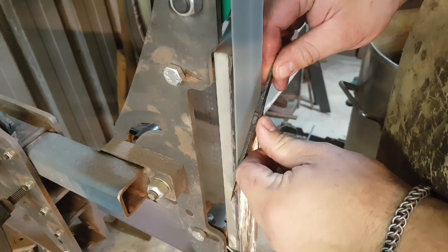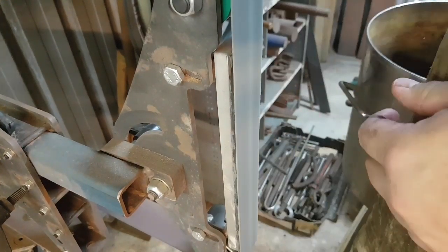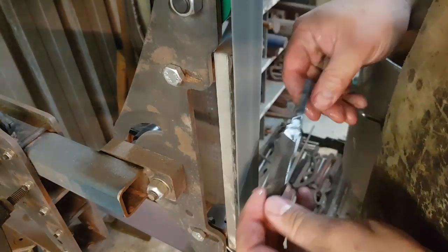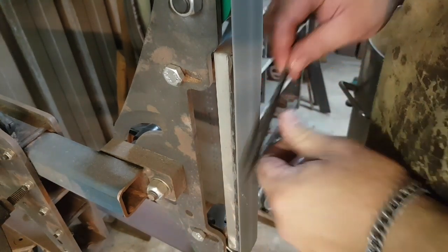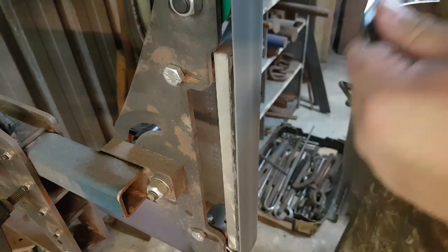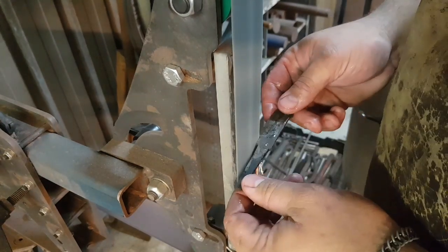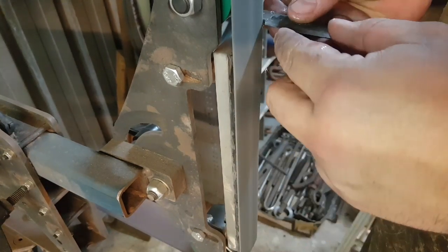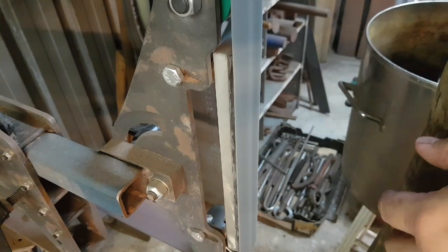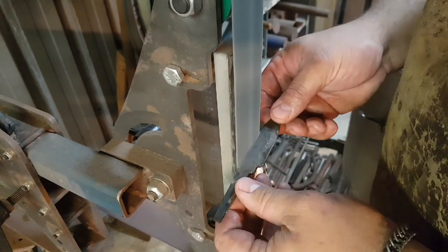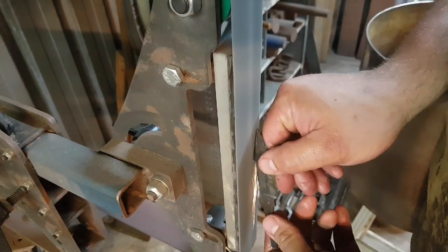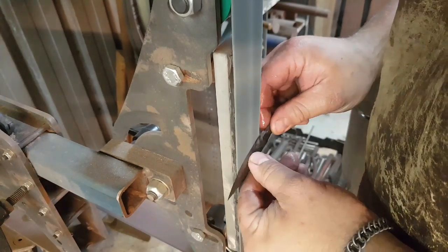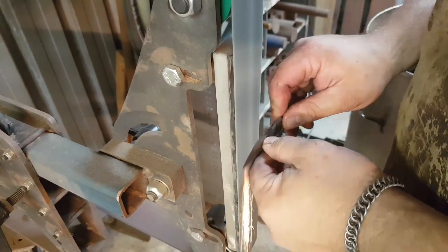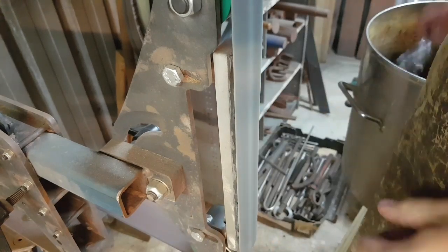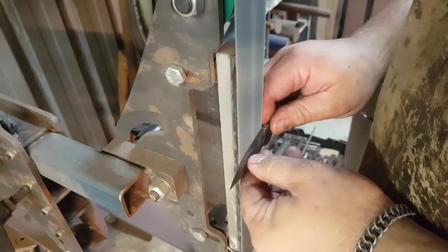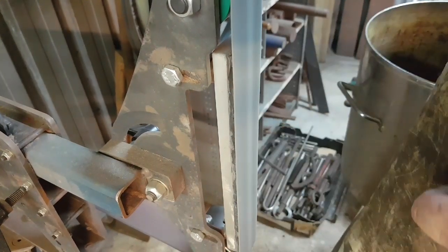Now I'm finished grinding, and I'm starting off with a 240 grit equivalent. It's an A60 belt, I believe, Trizact, and this will go straight to hand sanding from there. On a larger blade I might go to 400, but because this was so small I didn't want to overheat the blade, because if you do ruin your temper in this case, you also ruin the Hamon, because the Hamon is the differentiation between hard material and soft. So I ground this to a 240 grit finish, and then we go to hand sanding.